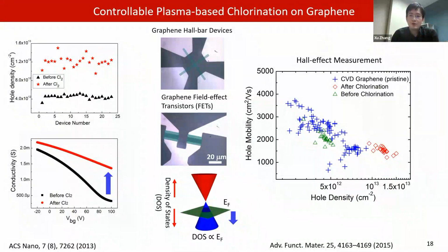We use an electron cyclotron resonance plasma chamber to generate chlorine plasma and dope graphene. The key is to generate a chlorine plasma with the lowest possible kinetic energy by fine-tuning an RF bias applied to the substrate. After optimization, we quantify the carrier density change in graphene. The hole carrier density in graphene was enhanced by about 3 times on average. Hall effect measurements and a statistics study also confirmed that the high mobility of CVD-grown graphene can be largely maintained after chlorination.